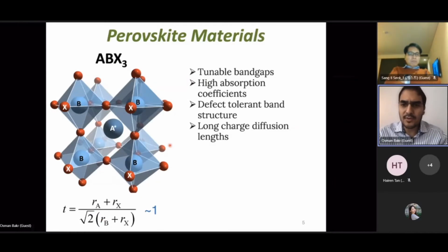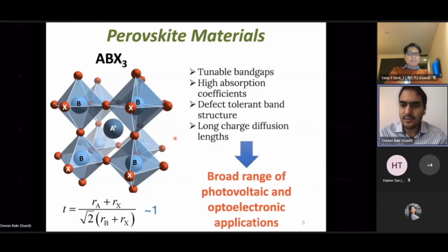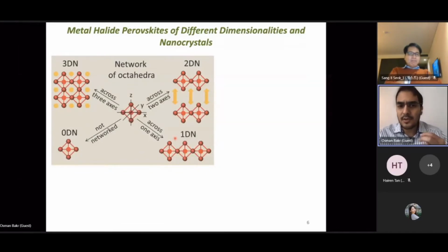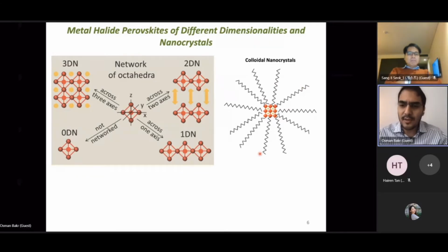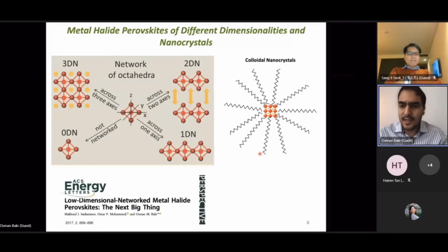Researchers are interested in perovskite structure because of its tunable band gaps, high absorption coefficients, defect tolerance, and also long carrier diffusions. So that means there's a lot of applications that we can consider for this outstanding semiconductor. But also, there's a lot of versatility in the structures that it forms. You could form the classical perovskite structure, but if you start adding large A-site cations, you could start breaking up the perovskite network. You could form 2-dimensional perovskites, 0-dimensional perovskites, 1-dimensional perovskites, and even if you use surfactants, you could start making colloidal nanocrystals. If you are interested in this topic, I would urge you to look at the perspective we wrote about different dimensionalities that perovskites can adopt.